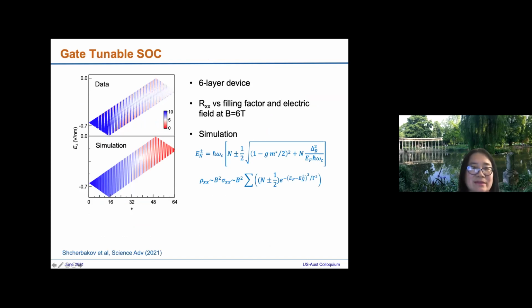We can also calculate alpha, this Rashba parameter, by looking at the oscillations as a function of charge density and electric field, and seeing where the crossing happens. That's where the node is. So by tracking how this changes as a function of density and electric field, we can simulate this.